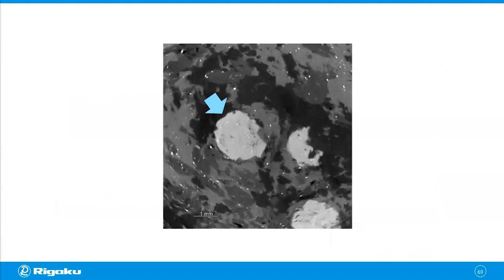Then you can always segment this inclusion like this using all those pixels. But if you use those pixels, you end up having this kind of shaggy looking interface line or surface. This is probably a better representation of the shape of this inclusion. And you can get this interface line or surface either by using an interface detection technique called ISO 50, or you